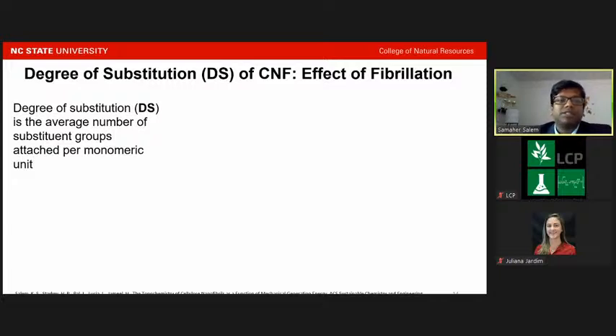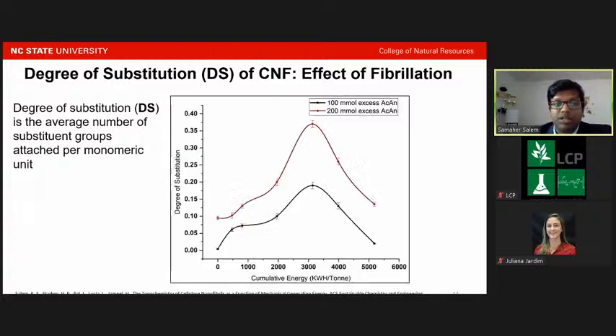Then we further measured the reaction and calculated the degree of substitution. The degree of substitution is the average number of substituent groups attached per monomeric unit. So we could say that initially, with the increase of energy, as the fibrillation increased, the degree of substitution increased. This part is up to 3000 kilowatt hour per ton energy. This part is kind of expected, because as we fibrillate more and more, hydroxyl groups will be exposed to the surface and will be available for the reaction and substituted by the acetyl group.